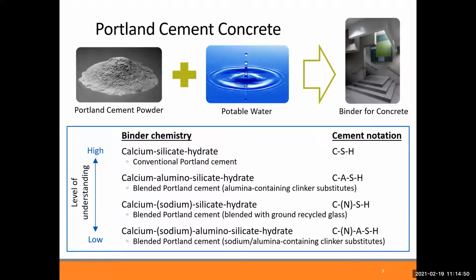But the calcium silicate hydrate gel is made when you mix Portland cement powder with water. It's a hydration reaction. Calcium silicate hydrate is one of the phases that precipitates out, along with other phases. There's 5 phases in the beginning, Portland cement powder. So it's a very complicated reaction process going on if you're trying to track everything. And so Portland cement powder mixed with water is the glue that holds sand and rocks together in the concrete, and you end up with concrete.